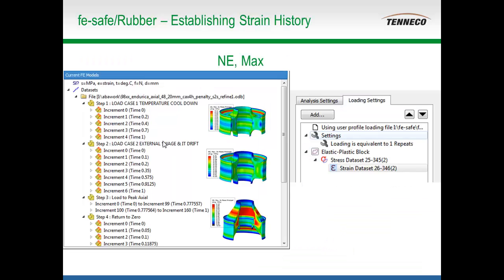This slide is showing the strain history that was established in FE-safe rubber. So what we're showing here is not necessarily how you would use FE-safe rubber in practice, but I'm showing this to kind of highlight that our starting part already has several states of strain in the part. So we have the thermal shrinkage from the molding process. So obviously elastomer parts, most of them are thermoset materials. So they're molded at 170, 180 Celsius. So you have the strains that are induced from the thermal shrinkage.